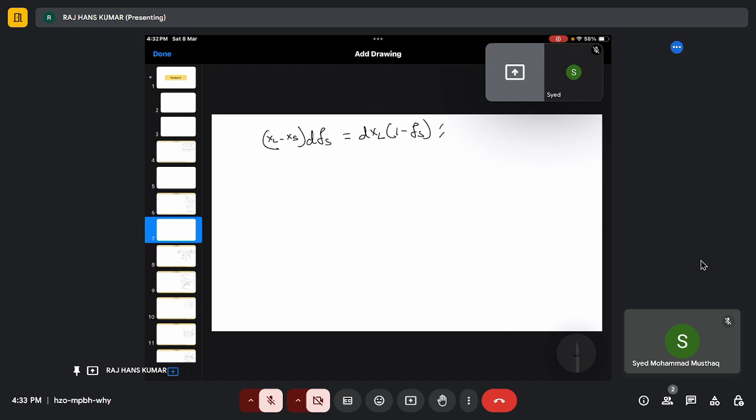Now, how do we solve it? To solve any differential equation, we need boundary conditions. Now, what are boundary conditions? Initial point. What is our initial point? At Fs equals 0, we have a boundary condition: Xs equals Kx0, where x0 is my liquid concentration at the first point.